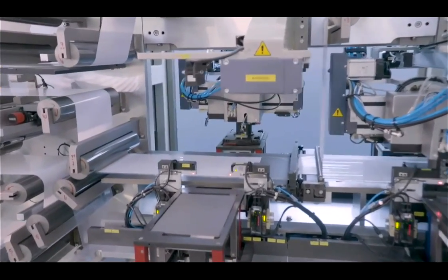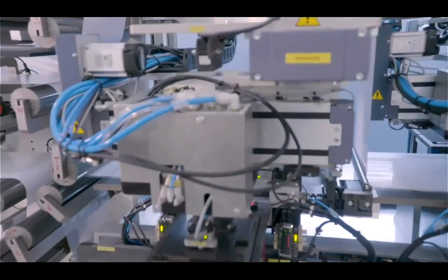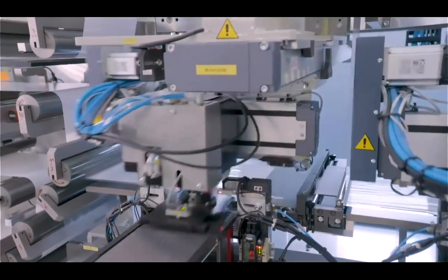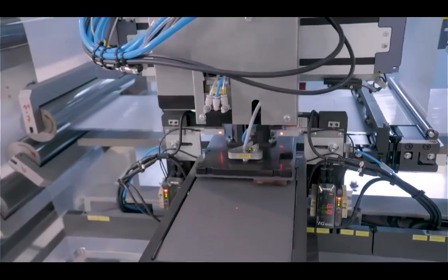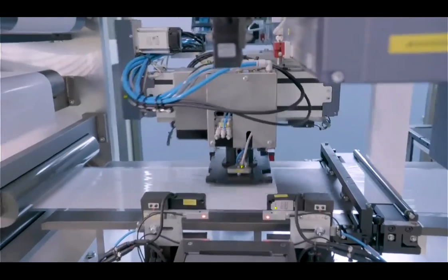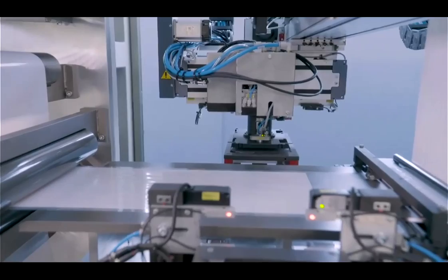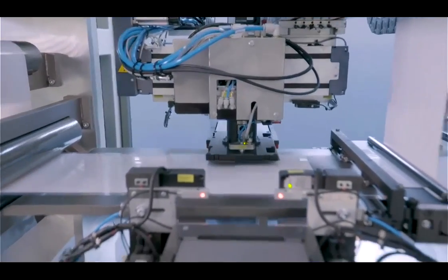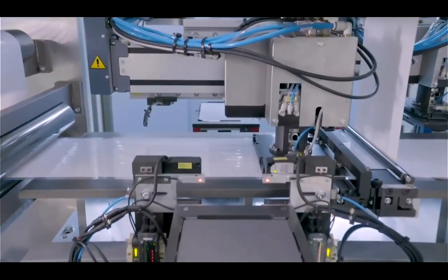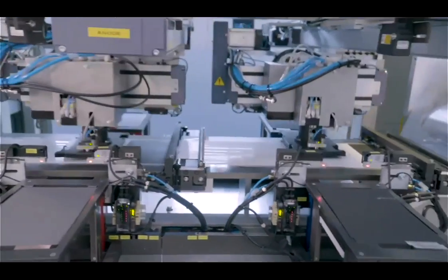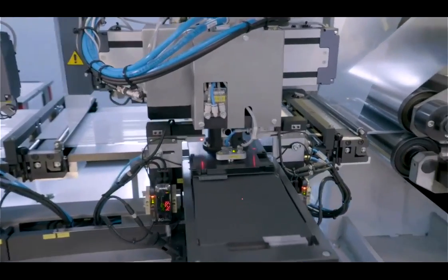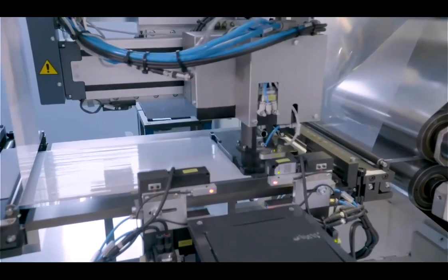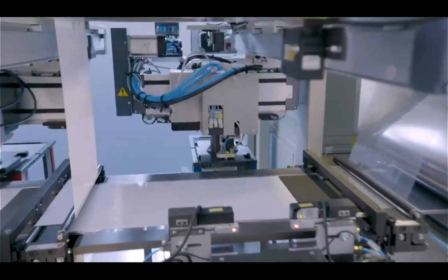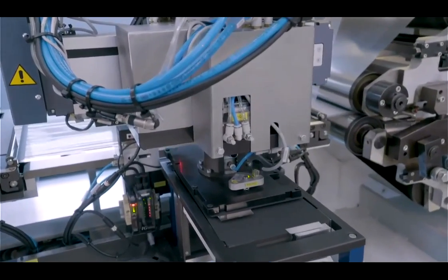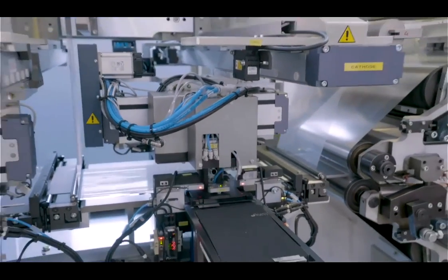So in this machine, we fit the roll of separator. We fit the box of anodes, the one that you are seeing in the image, and we fit the box of the cathode. So in this case, the anode and the cathode sheets are inserted in the separator, and the separator is used in the form of an endless tape, and it's cut off after the stacking process. So in this equipment, the exact positioning of the individual sheet is considered the central quality criterion. Okay, it's really important, this point. So here you are seeing the same as in the previous machine, that the sheets are transported by vacuum grippers.